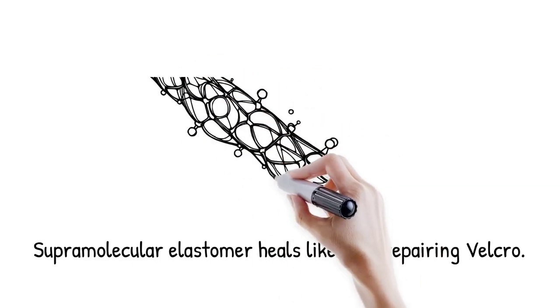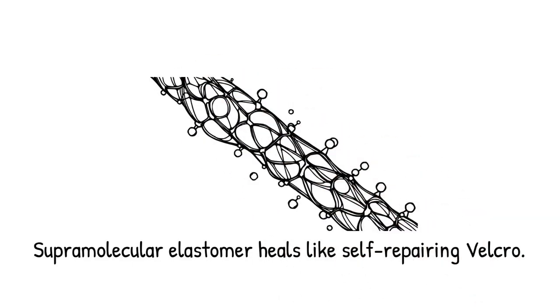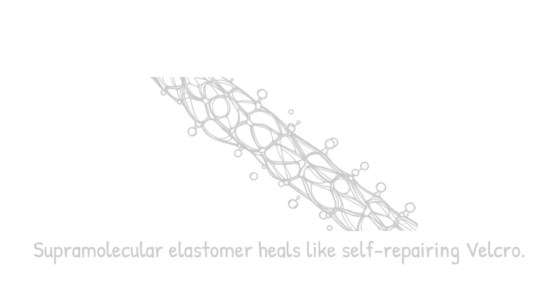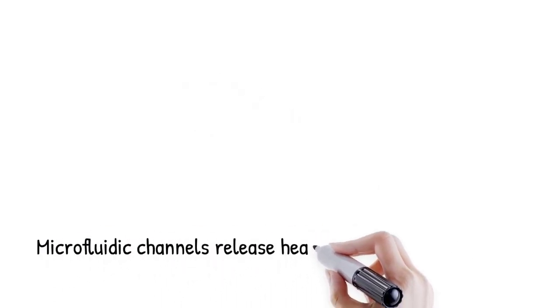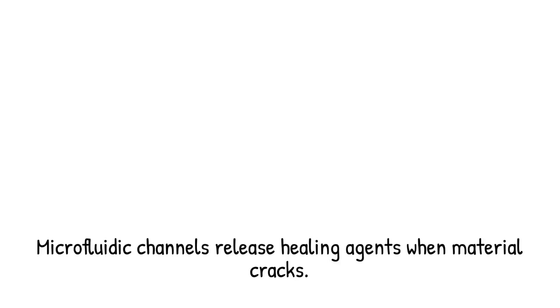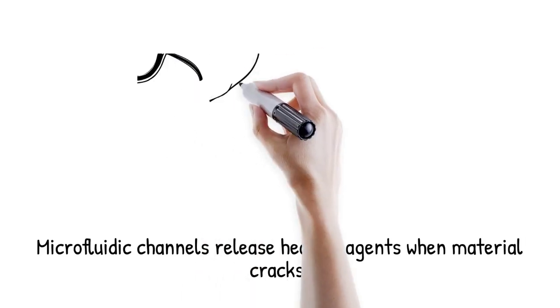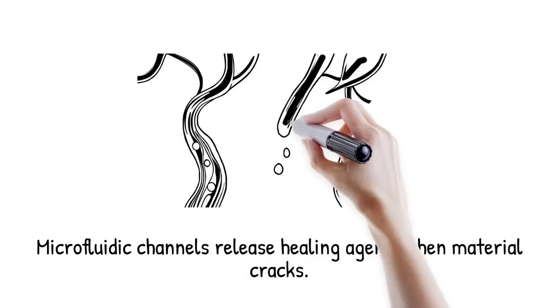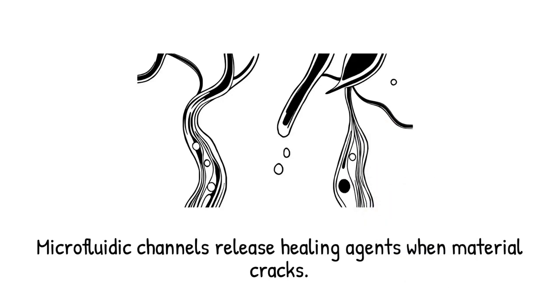A supramolecular elastomer using cyclodextrin-adamantane pairs fully healed surface cuts overnight at room temperature. It's like Velcro strips that detach under force but reattach themselves when pressed back together. Inspired by biological vasculature, synthetic biomaterials embed microfluidic channels filled with healing agents such as monomers, catalysts, or nanoparticles.